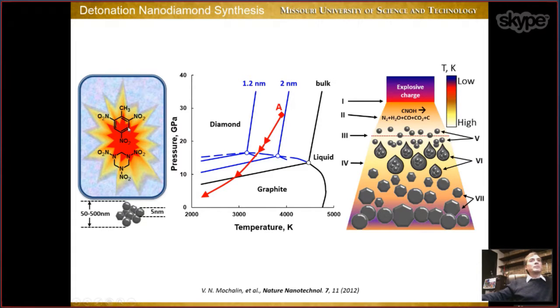So the excess of carbon atoms present in these molecules of explosives starts to form diamond phase. And it starts to grow, but again, detonation is a very short process. Pressure and temperature drop quickly back to normal conditions. So the growth is not prolonged. It stops very quickly after the growth was initiated. And basically, your system moves along this red line from A to the domain of thermodynamic stability of graphite, and then eventually, when temperature drops below 2000, everything stops. So nothing changes, and you have nanodiamond formed.